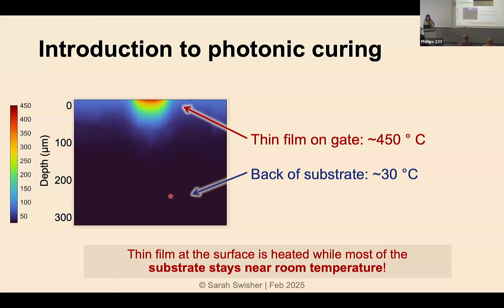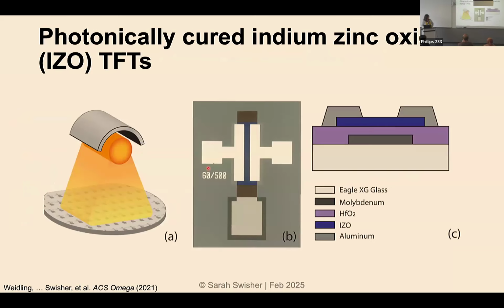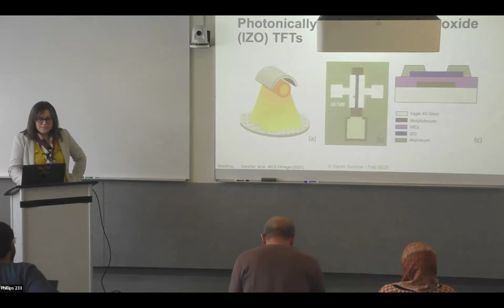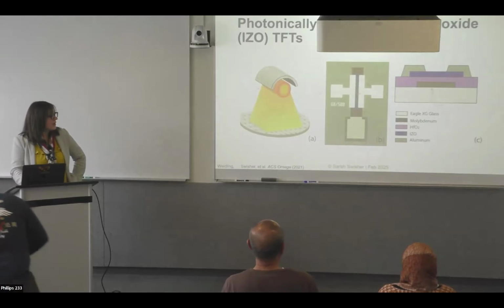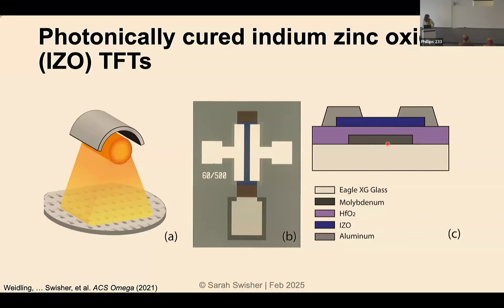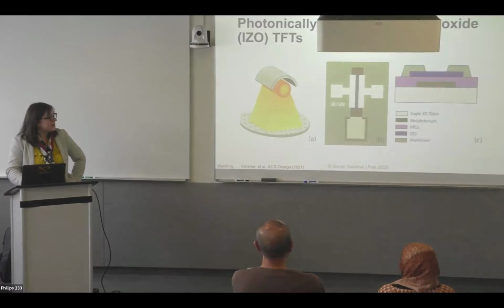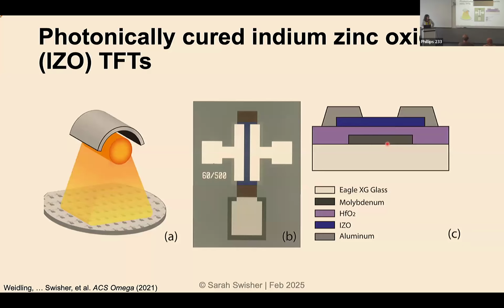So to use this to make our indium zinc oxide transistors, we make pretty big devices in my group. So this is a 60 micron channel length. So we make fairly big devices. This is a 60 micron channel width here. And the stack looks like this. So we're working here on glass substrates. We have a molybdenum bottom gate. That's a really good absorber. And it doesn't reflect the light. So we can absorb about 60% of the energy from that xenon flash bulb. Then we use a hafnium oxide gate dielectric, and this blue layer is our indium zinc oxide semiconductor. And when we do the curing, we do it without the source drain in place. So here I'm showing those top source drain, but those would not be there when we do the curing.